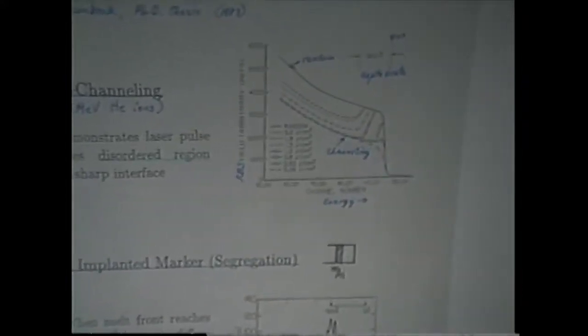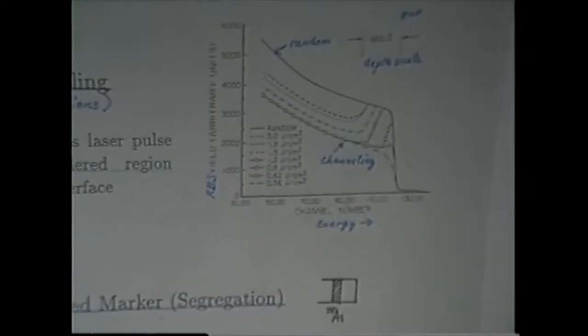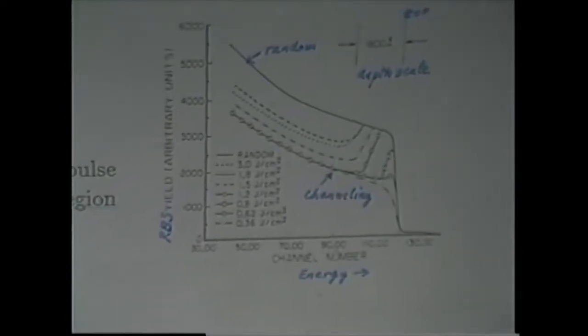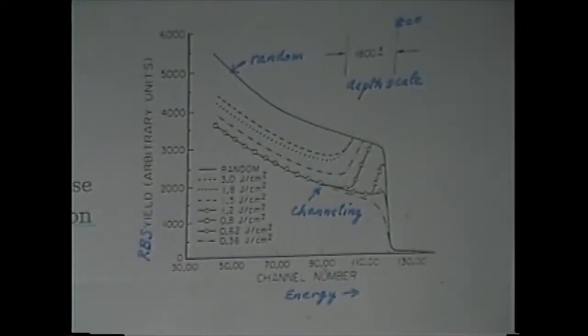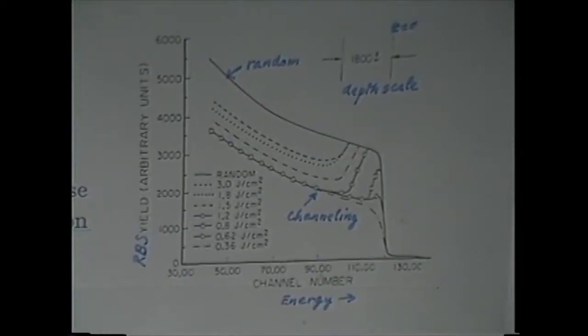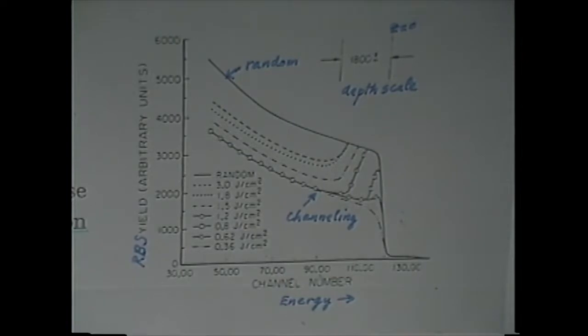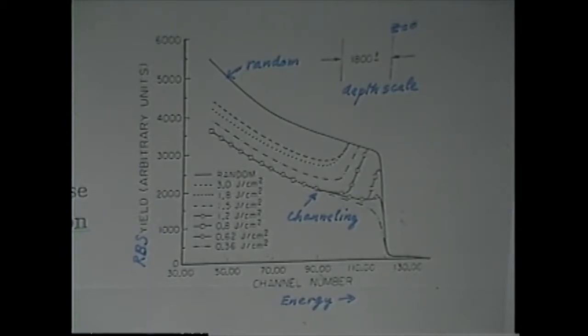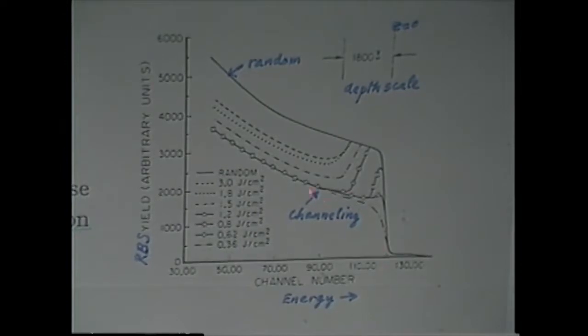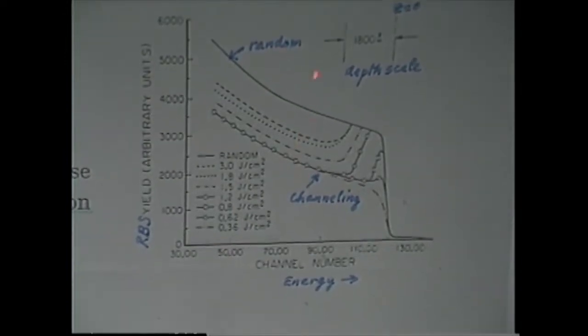However, when the beam is tipped away from the c-axis by even a fraction of a degree, then there'll be copious scattering of the carbon atoms, and we'll be up in this range, the random range. Now, if we introduce disorder in the crystal, that is, we don't have a very well defined c-axis and it's off by a bit, then we'll go from this channeling level to the random level.